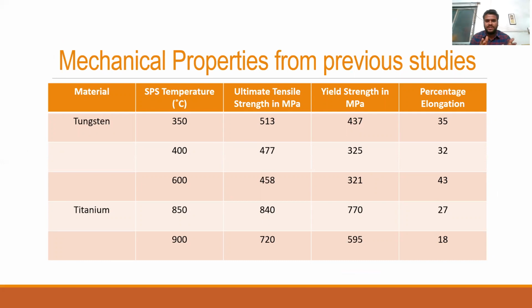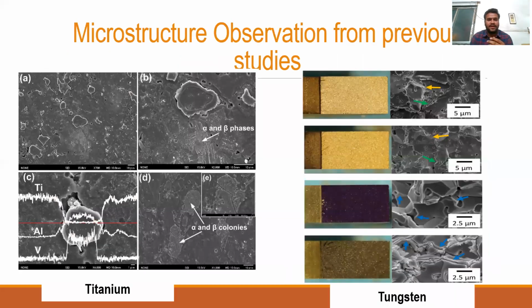These are the mechanical properties found from the previous studies, where you can see tungsten and titanium were sintered at various temperatures. At 350 degrees Celsius of SPS for tungsten, the tensile strength was 513 megapascal, yield strength was 437 megapascal, and percentage elongation was 35. Similarly, for titanium at 850 degrees Celsius, you can see the tensile strength, yield strength and percentage elongation from the table.